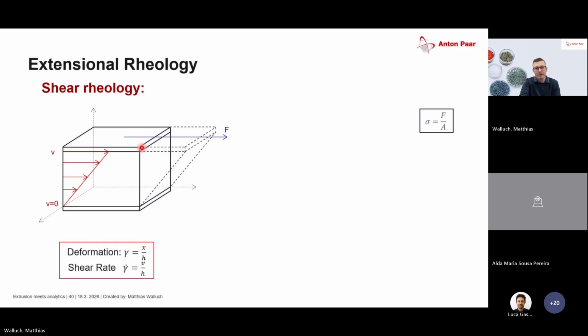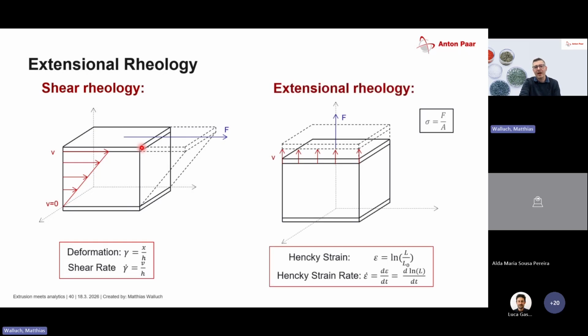Here we have the sample, and here we do not shear the sample anymore, but we stretch it. So the sample is not getting sheared, but it's getting longer and longer. So we have a certain strain rate instead of a shear rate. And we have a strain instead of a deformation.